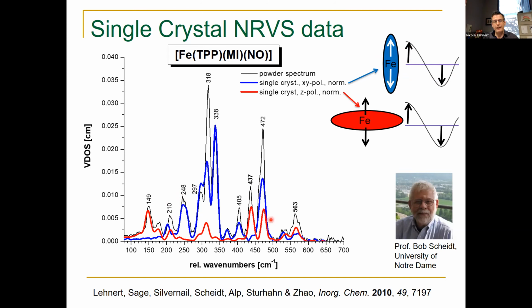And so now we can get the spectrum here. The red intensity is iron moving out of the heme plane, right? And so we can actually now, based on these measurements, distinguish the direction in which iron is moving. And what you note, of course, is that this 437 wave number band is exclusively out-of-plane polarized. There's pretty much no blue intensity here, whereas that feature at 563 wave number shows this kind of mixed polarization with blue and red intensity as well. So this is really important information now that we can use for our analysis.